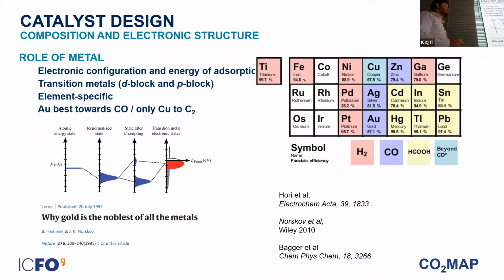One of the things that is more or less understood now too is that the impact of the metal is key. So for example, there are metals that are well known to generate hydrogen here. And this is mainly determined by their electronic properties. There are metals that are well known to generate carbon monoxide. For example, silver and gold are very well known to do that. But interestingly, there is only one well-known element able to generate multi-carbon products using electrochemistry. So carbon-carbon coupling, and this is copper.